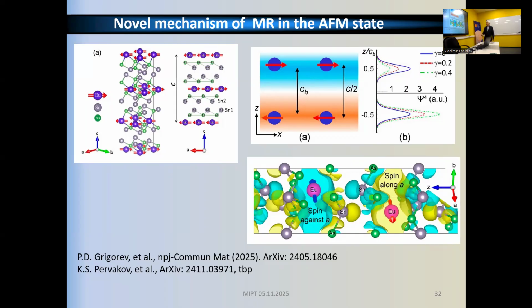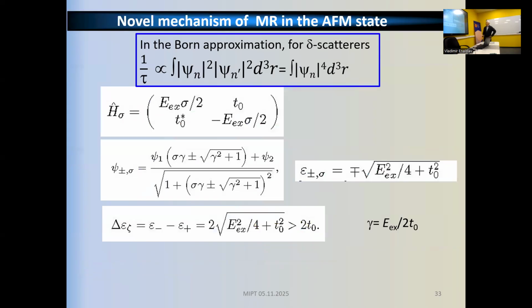It has a very simple effect, because even in the Born approximation, when you step back just to say that experimentally we see that this is a very isotropic phenomenon. If this is isotropic, then it immediately prompts us to consider point-like scattering. Just a common sense argument. Then we open textbooks and write down Born approximation for the scattering.